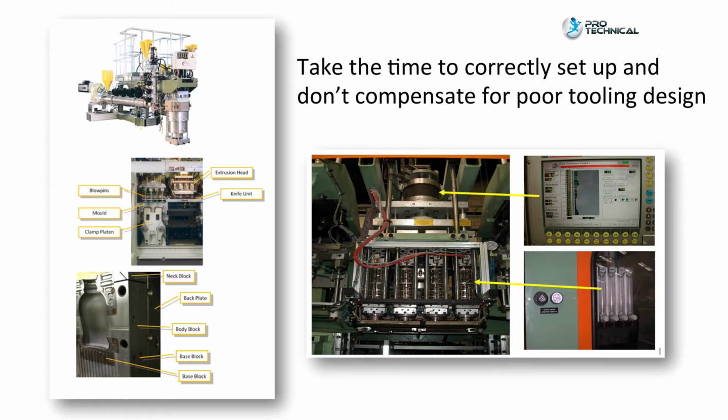So an extruder position, for example, doesn't change, nor does the wall thickness controller. It doesn't change either. However, the parison may change when the extruder die is dirty, or you have a faulty thermocouple, or changes in weather. The temptation is to adjust the extruder position or wall thickness controller. You must resist this temptation. Clean the extrusion die and check your machine settings against your data sheets.